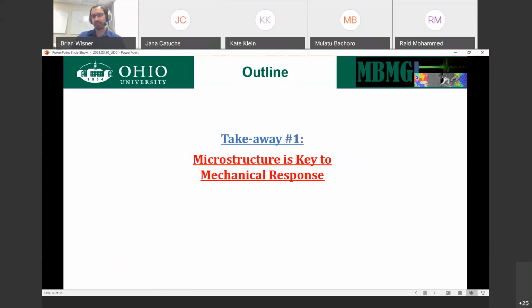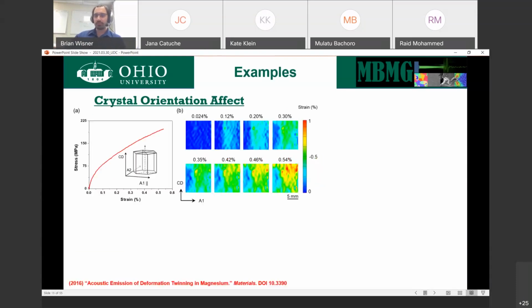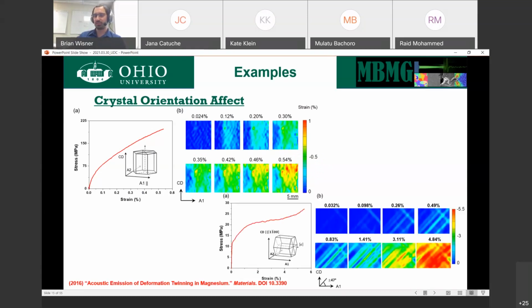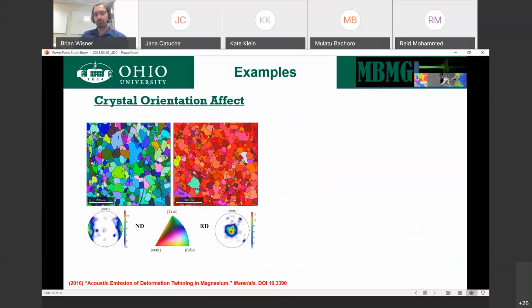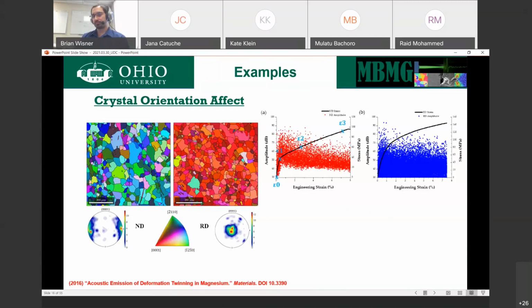First, the microstructure, as I've been emphasizing, is key to the mechanical response. How do we know this? Well, here's an example of a magnesium single crystal compressed. First, along the C-axis, so compressing it in one direction, and then compressing the same material in a different direction. Just by looking at the color maps, the DIC results, we see a huge difference in the way the material is responding. We see a difference in the mechanical behavior as well, but that mechanical behavior comes directly from what the damage mechanisms are. That comes directly from the crystal orientation. Depending how we manufacture, we can achieve preferential directions in one of these orientations or the other. If we do, we end up with a material that has preferential orientation and ultimately has different mechanical behavior. Makes sense.